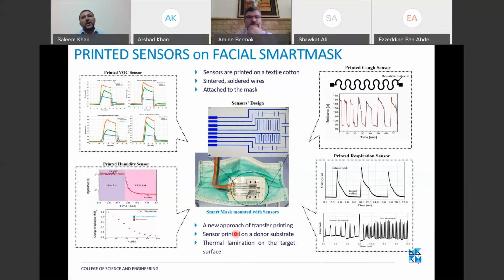Now, currently, we are working on a new approach where we can use a transferable technology, which is more convenient, because here we deposit the printed structures on a donor substrate, and then we use thermal lamination and deposit directly on the substrate, where we will avoid the delamination. In this case, we are using an adhesive tape that we can remove. So these were the different sensors that we fabricated and tested in the lab.